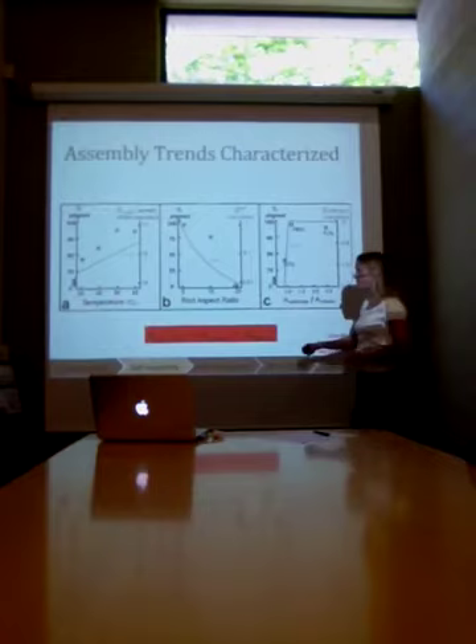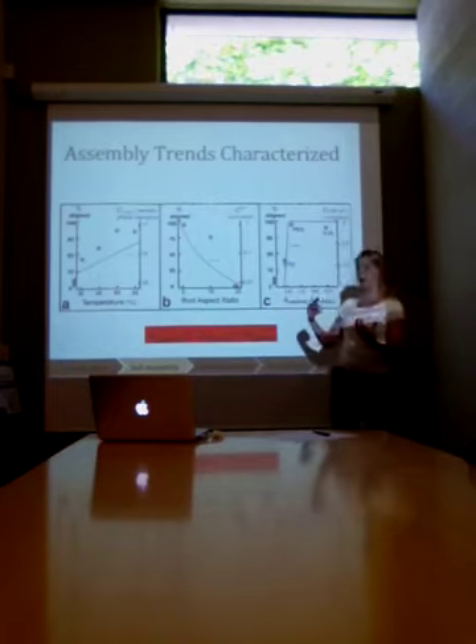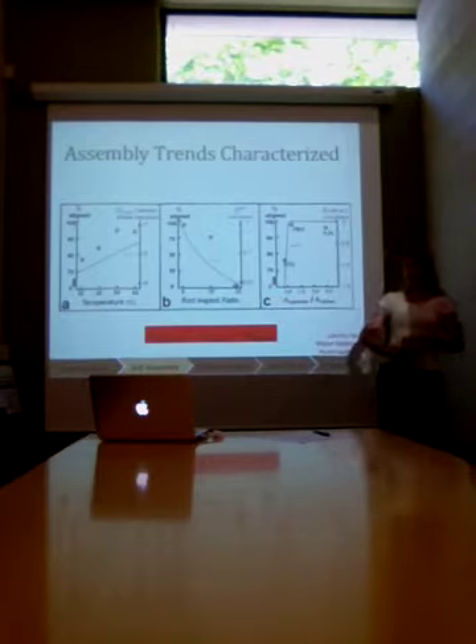And so we could map out the entire parameter space by looking at the degree of rod orientation as a function of temperature. We found that temperature did help them reach alignment, which was in keeping with what happens in a nematic phase transition in liquid crystals. We also found it was difficult to align rods the longer they get, which was consistent with the fact that the rotational diffusion constant gets slower and slower the longer those rods get, and it's just kinetically difficult to align